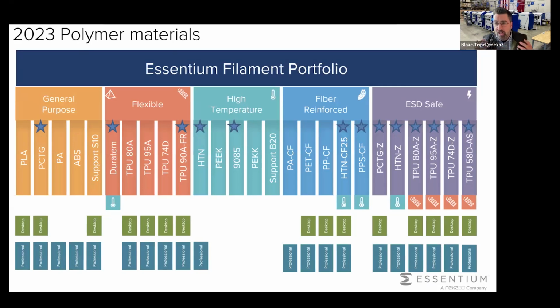So we basically modified the polymer backbone of polyether imide. I won't get into detail how we did that because it's super esoteric. I love it, but if you want to learn more, reach out. But we modified the chemistry of Ultem in order to make it more flexible. So now if you print an Ultem part and you drop it on the floor or something, you don't have to worry about, did I crack my part? Because Ultem is incredibly brittle. So by creating Duratem, we've created a durable Ultem, and that material was just launched last year, and we couldn't be more excited about it.